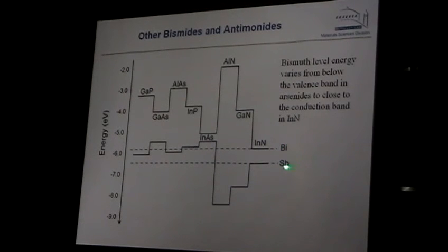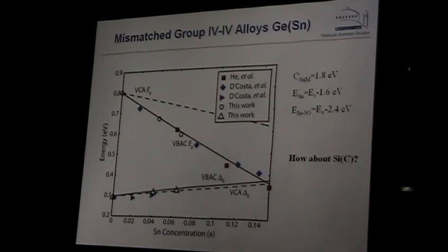However, incorporating bismuth and antimony is really difficult. We forced many elements into unfriendly territory, but so far we were not successful in putting bismuth or antimony into gallium nitride or aluminum nitride, because these materials have extremely small lattice parameters. So big elements like bismuth and antimony don't want to go in. But we synthesized some: we have gallium phosphide with antimony, gallium arsenide with both bismuth and antimony, and indium arsenide with both. So there is a lot we know now.